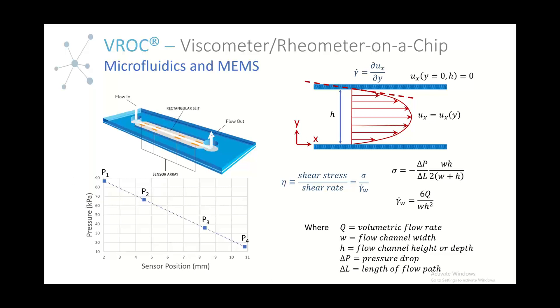For battery solutions, we use our Initium technology, which is our high-throughput automated viscometer rheometer. Battery solvents are volatile, and Initium is a closed system, so it can eliminate any artifacts that might occur due to evaporation of fluid. Battery solutions are also low-viscosity fluids, and Initium is ideal for low viscosity measurements with high accuracy. The lowest viscosity measured in our experiments for battery solvents is around 0.4 mPa·s. These are the two main reasons we decided to use Initium for measuring the viscosity of battery solvents.